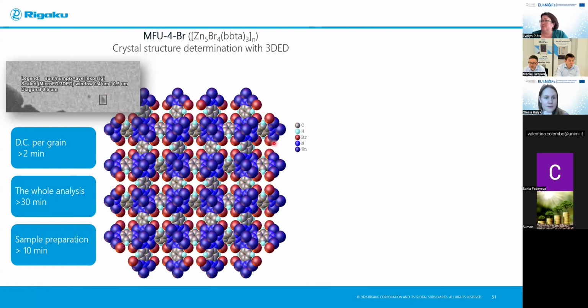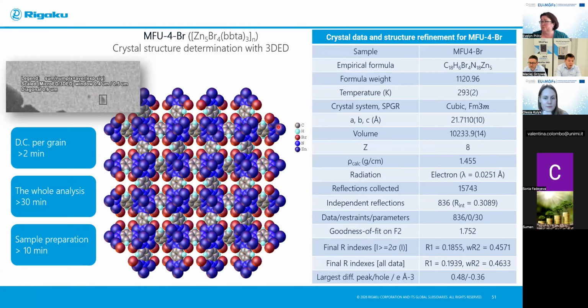So you can see a picture of the solved structure, and here are the parameters that we later use for further analysis. And as you can see, the grain, you can see the slightly larger cubes, there are leftovers, but the small grain, the diagonal here is less than half a micron, and it just gives you an idea of how quick this analysis can be. So as I mentioned, it's just 2 minutes per grain. You usually measure several grains just to have better statistics. So the whole analysis is 30 minutes, and the sample preparation is 10 minutes.